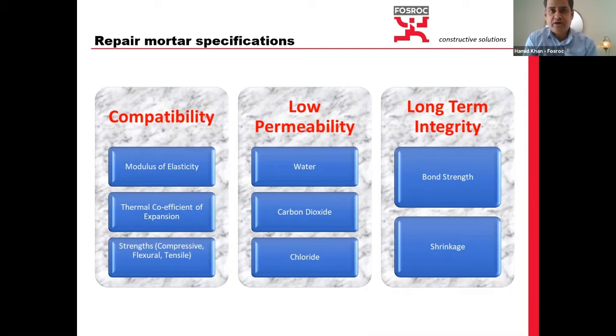And these shrinkage values are specified, sometimes, as I've seen, by different asset owners and engineers, based on the type of the structure and also based on the environment. For example, in marine environment, these values are more stringent. And same is with the chloride testing and chloride diffusion resistance as per NT Build 443. If they are non-marine, they are a bit lenient. If they are benign, they are a bit lenient. So it depends on the structure as well, but these factors must be considered. And same is with the bond strength. Very important to have a good bond strength for these repair mortars.